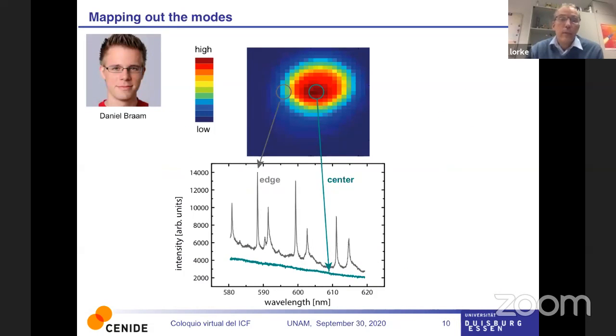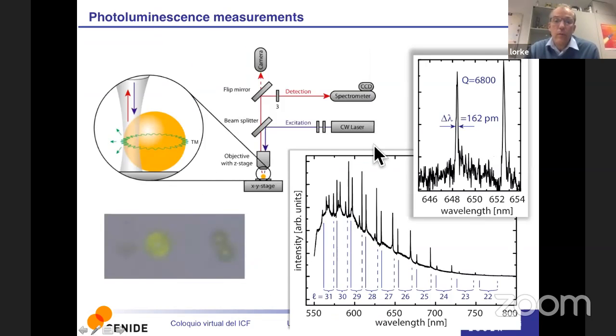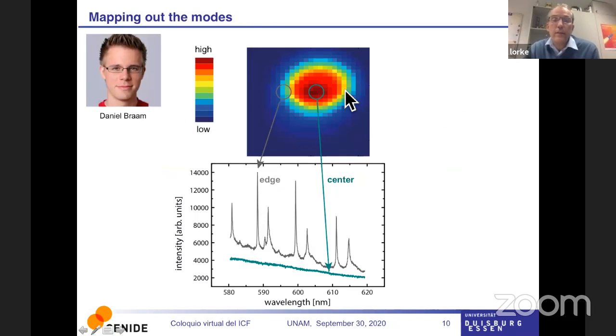And Daniel Braam, the PhD student who did these studies, then took a closer look because our microscope has an XY stage. So you can locally excite these spheres and look at the light that comes out. And he saw that when he looked at the edge, he sees these resonances quite nicely. And when he looked at the center, he didn't see anything, which of course is nice, because that's what we thought. We thought it goes around in circles.